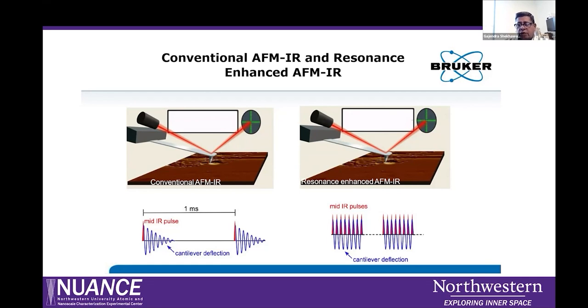Then there's also tapping mode IR, which uses the conventional tapping mode cantilevers. They are all metal coated. In tapping mode, we excite the cantilever at its resonance frequency, and then we can implement the phase-locked loop on that option. Tapping mode, as you have seen, has a better resolution than contact, and it is also more friendly for softer materials. If you have a very soft material, because of the lack of shear forces, the probe will not scratch the surface, as compared to contact mode, which is good for hard materials. When it comes to soft materials, use tapping mode IR.